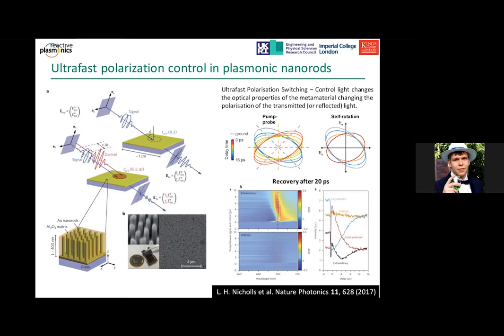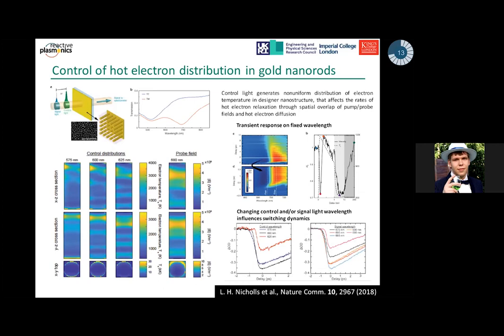We indeed are able to observe the strong rotation of the probe beam, as well as change in ellipticity governed by the control beam, as well as the rotation without the control beam if the probe beam is made powerful enough, the so-called self-rotation. We further built upon this idea by making the structure optically thick, in which case we can produce a hot carrier population which is non-uniform inside the structure and also evolves by itself through the photoelectron diffusion and photoelectron decay in the material, and while during the evolution interacts differently with optical modes in the structure.